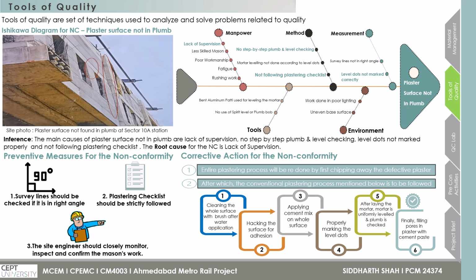The main causes of plaster surface not in plumb are lack of supervision, no step-by-step plumb and level checking, level dots not marked properly, and not following the plastering checklist. The root cause for this NC is lack of supervision. The contractor's engineer did not supervise the work efficiently. No inspections were made at different intervals, which led to errors being unchecked, and the defects prevailed, which led to defective plastering work.